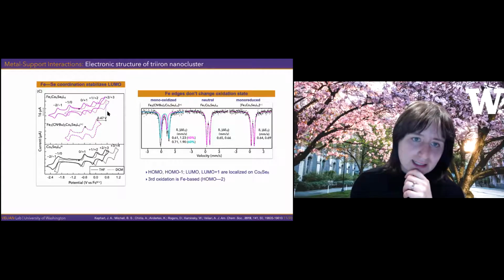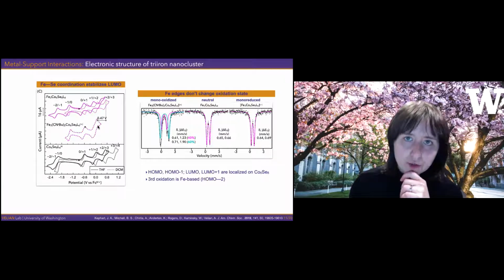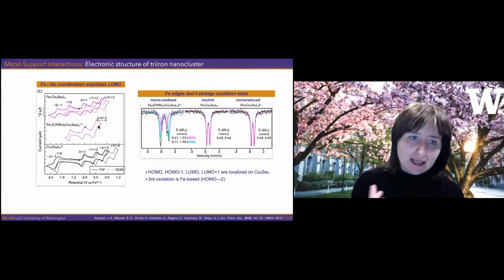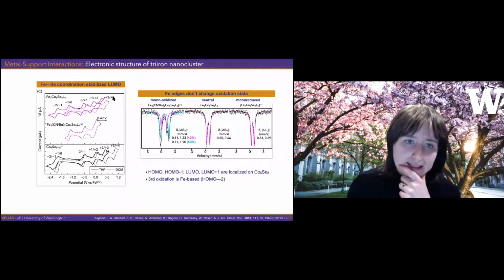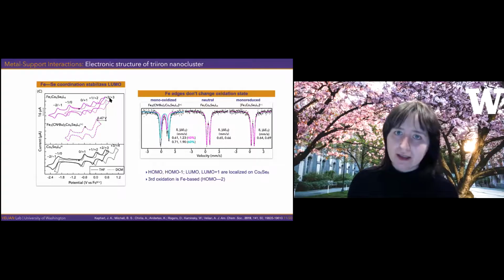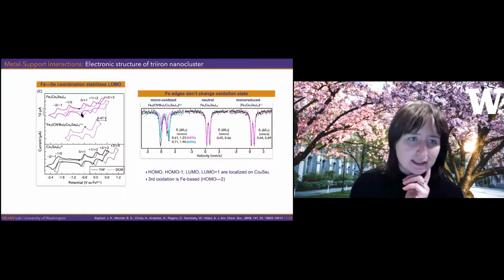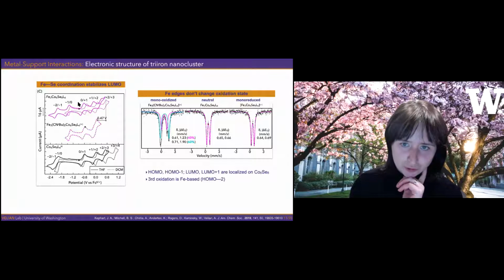And what we see is that this third oxidation responds by changing by half a volt when we have isocyanide coordinated to it in the way that you would expect. And so we think that this is associated with the iron oxidation. So the iron states are really buried in there. They're not at the valence level, the HOMO-LUMO, which we think is here.